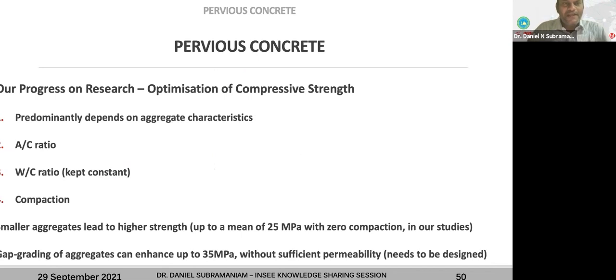And then we have optimization of compressive strength. So compressive strength can be optimized using aggregate characteristics, AC ratio, water cement ratio, and compaction. So water cement ratio, we are going to keep 0.3. It is almost universally accepted. And then small aggregates lead to higher strength. We actually got up to about 25 megapascal without any compaction at all. Right, so small aggregates in the way that I mean, about 2.36 to 5 or 8 millimeter particles. Now you may wonder whether it has permeability.